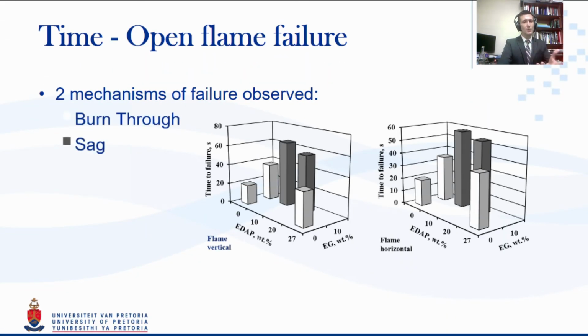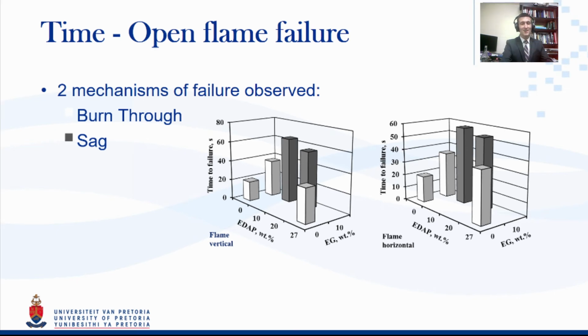So we observed two mechanisms of failure, burn through and sag. And here we actually found that if it prevented burn through entirely until it was fully melted, that was actually a really, really good result, because it still maintained some of its structure up until that point and thus delivered some really good results. In all of these cases, once again, the binary systems really exceeded our expectations, giving some really good cohesive expansion and some good thermal barrier behavior.